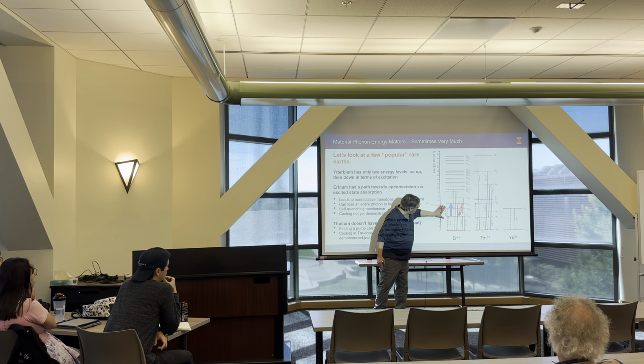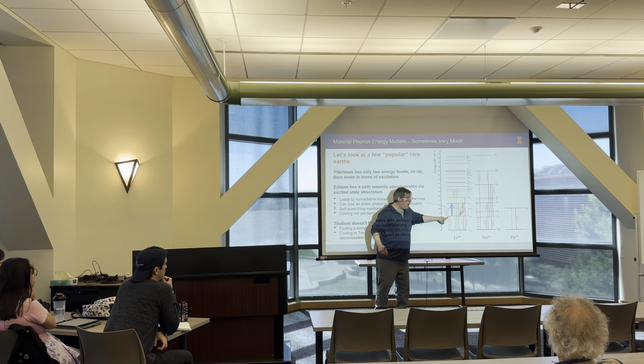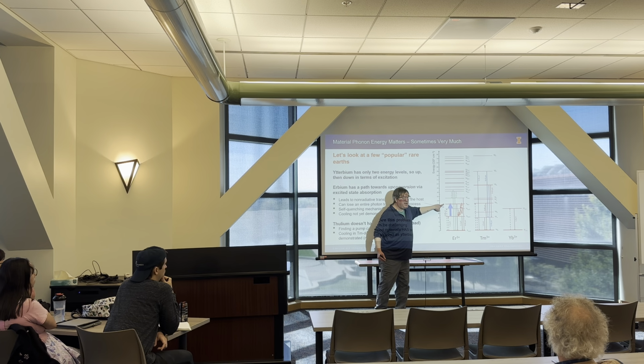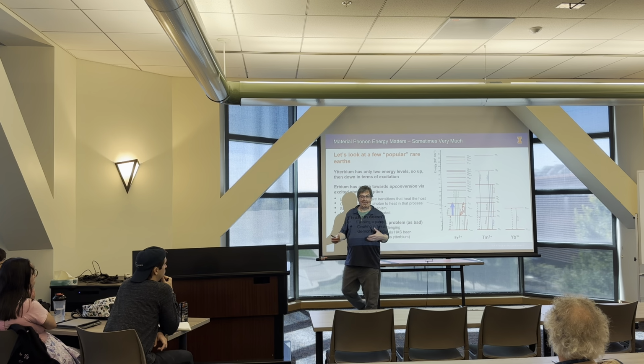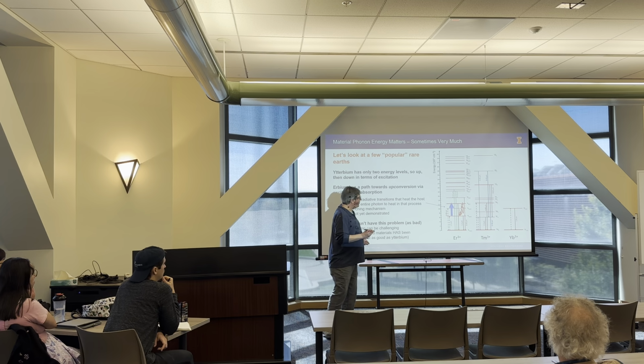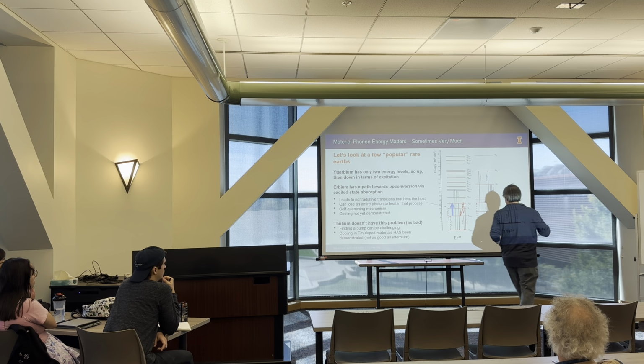You're excited, but now look, this energy spacing and this energy spacing is about the same. So what will happen potentially is that instead of spitting out a photon, you absorb another photon and you end up over here. Well, these energy spacings are such that this becomes a non-radiative process. And so the photon that gave you upconversion relaxes back down to the original state through the production of heat.